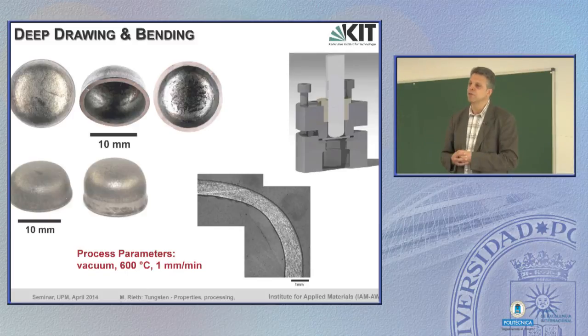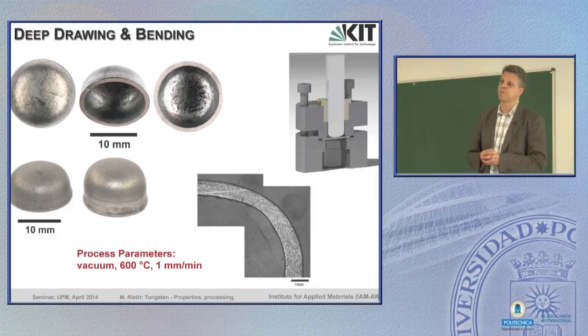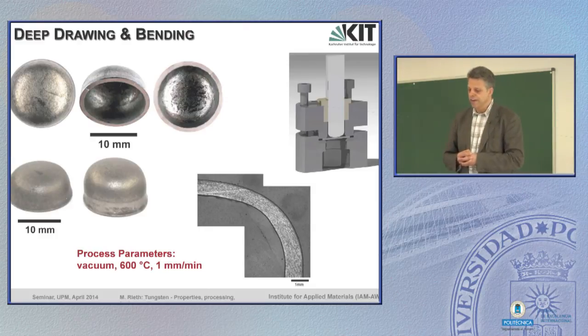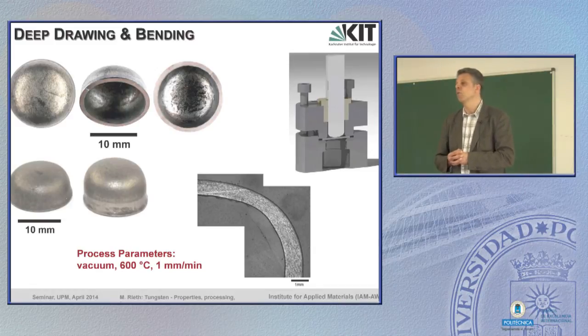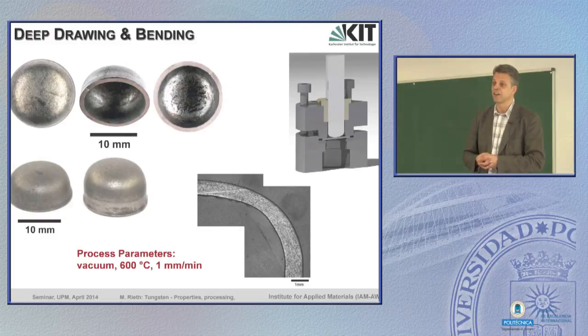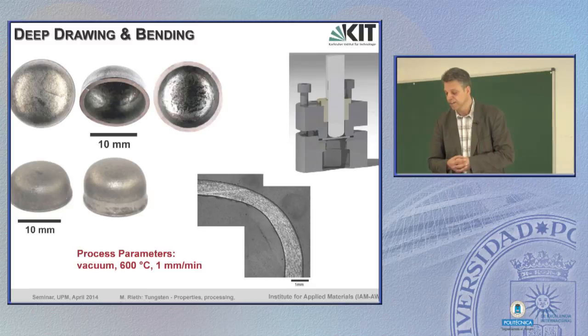well, only medium temperatures. Let's say 600 to 800 C is perfectly enough to deep draw these materials, also to bend these plates. But the bending rate or deep drawing rate is so slow, with about 1 millimeter in this case per minute, that the usual benefit of this method, namely mass fabrication, fabricate such parts by the thousands or millions, is not possible anymore.